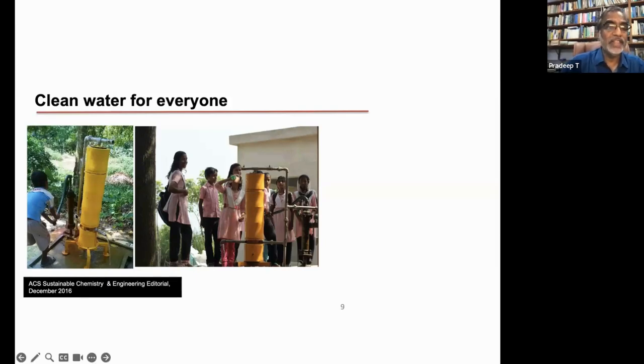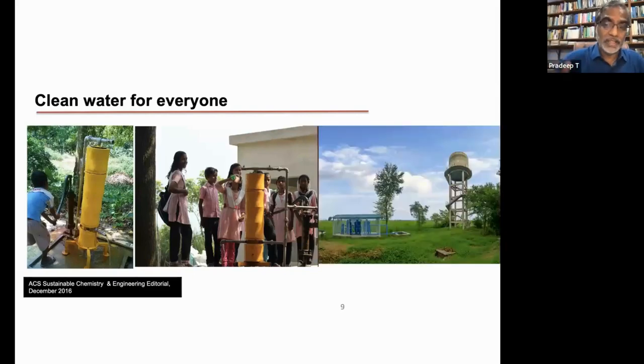So we connect this device there, which contains these materials. You pump, a stroke of this pump by this boy delivers 300 ml of water with a contact time of about 2 seconds. The arsenic is removed and you get clean water here. One stroke gives you 300 ml. That means 3 strokes give you a liter. So it can be put in schools, and therefore it has gone on to several schools across the country. And there are 1.5 million pumps of this kind across the country in the affected areas. So, well, that is about that. But then of course you can take it to a larger scale as the community purification unit.